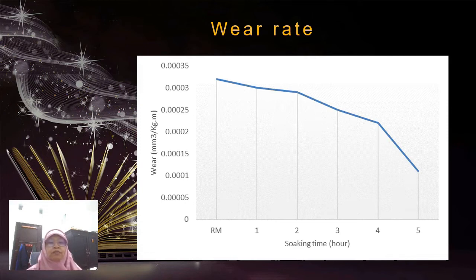The DCT process reduces the wear rate, which decreases with the higher soaking time. The 1 hour DCT process showed a wear rate of 0.0003 mm3 per kilogram meter. There was a decrease in the wear rate of about 6%.